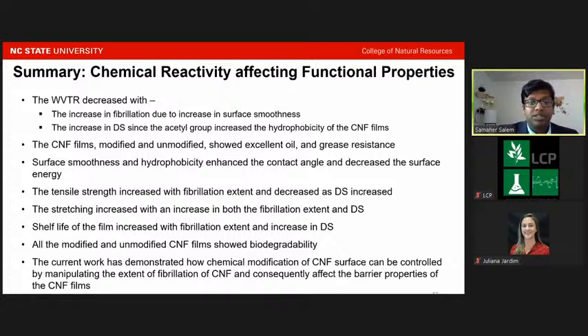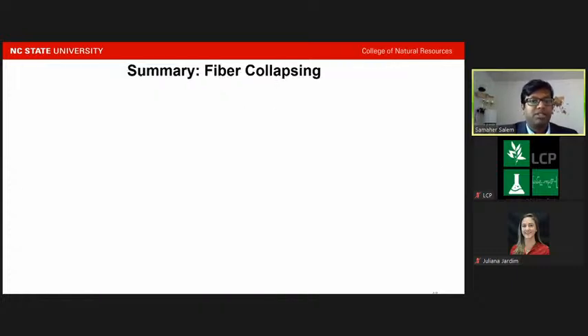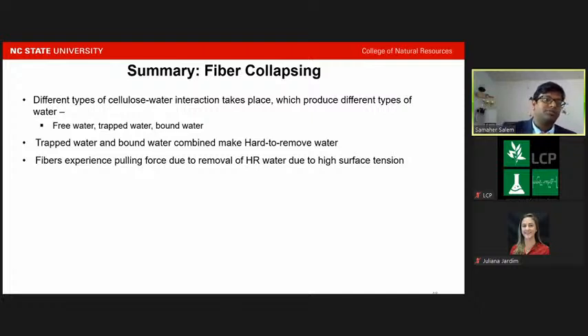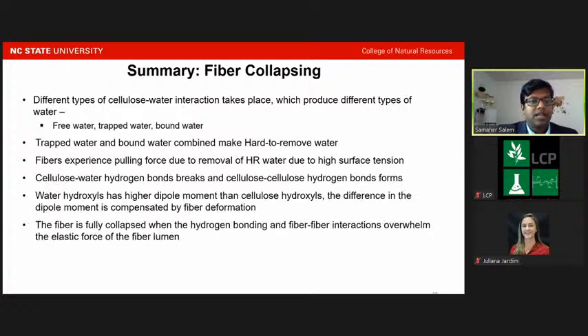And this work has demonstrated how chemical modification of the nanofibril surface can be controlled by manipulating the extent of fibrillation of the nanofibrils and consequently affect the barrier properties of the CNF films. We also show that there are different types of water present on the cellulose surface and how the trapped water and bound water, forming hard to remove water, affect the fiber collapsing due to high surface tension.